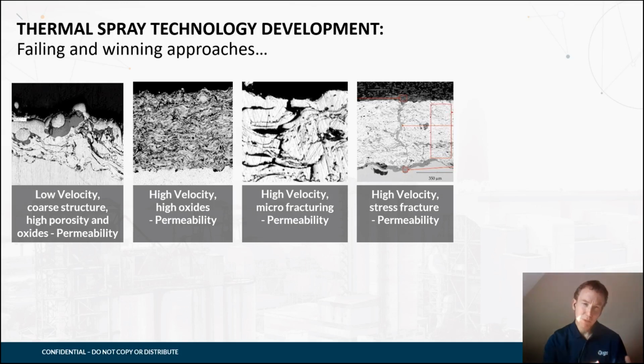So thermal spray processes and the class of technology we use are critical to see the long-term performance that we need. A low velocity system creates a very open microstructure which has opportunities for immediate permeation to the substrate, so that would lead to failure. High velocity systems, we create a denser microstructure, but if we don't control, for example, the oxide content, then those oxides are embedded into the system and create a weakness and a pathway to the substrate.